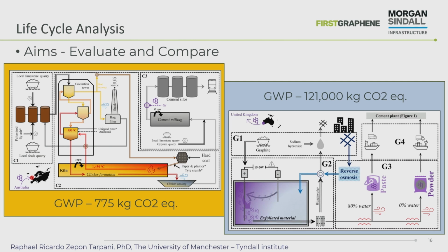They did a full life cycle analysis of both processes, the cement production process and our graphene manufacturing process. And this is the kilos of CO2 equivalent per ton in each of the products. You can see here, this is published, so it's not a secret, but on Breedon cement it was 775 kilos of CO2, and in our graphene, it's 121,000 kilos of CO2 per ton. Obviously, that's huge, and this was one of the outcomes of the project, to identify how much embodied CO2 our graphene had.